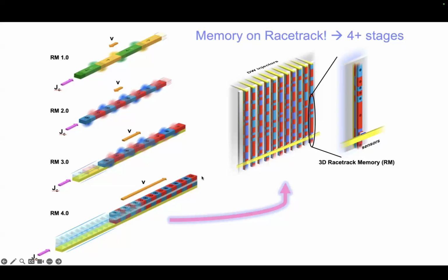And therefore, we can create a racetrack in which the top layer of the racetrack has a magnetization exactly opposite and equal to the lower racetrack. This means we essentially eliminate the magnetization. And it turns out when we did this, we discovered that the spin orbit torque generated again in this spin orbit coupling layer also gives rise to a giant exchange torque related to the strength of the antiferromagnetic coupling of the upper and lower racetrack. And so it turns out in this system, the domain walls will move at speeds exceeding 1 kilometer per second, 5 to 10 times faster than in an identical racetrack in which the upper and lower layers are coupled ferromagnetically. So this synthetic antiferromagnet turns out not only to eliminate stray fields, but it gives rise to a highly efficient current-induced motion of the domain walls. This is essentially why racetrack is possible today.